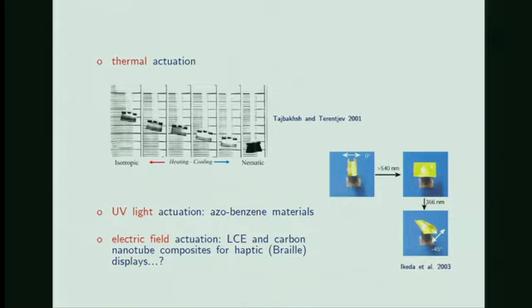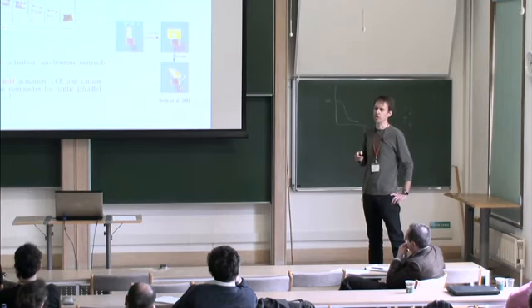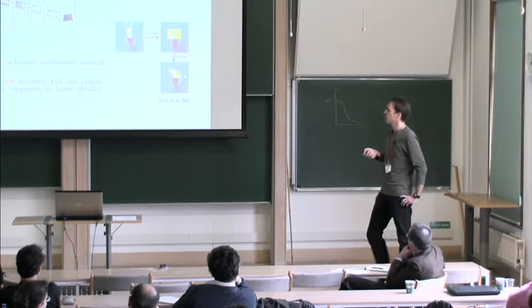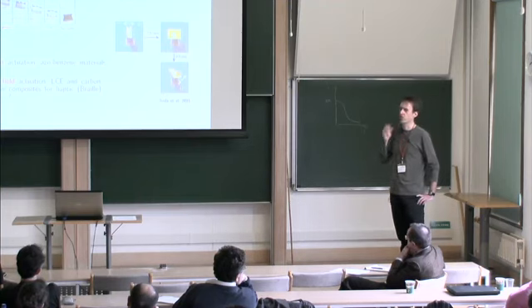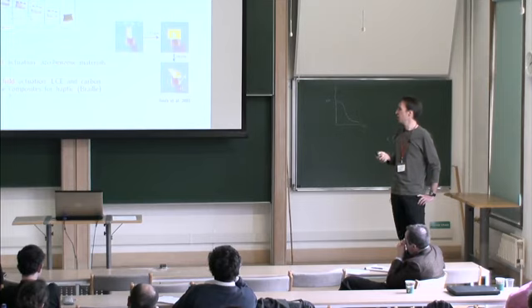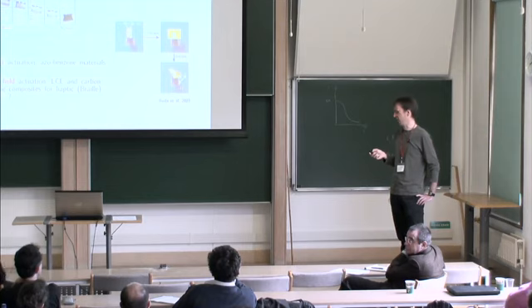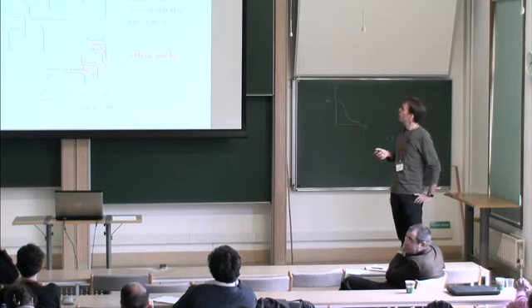Then UV light actuation. This can be done in so-called azobenzene materials, where double bonds between nitrogens can be found in different conformations, affecting orientational order. So you can switch between various orientations and affect the degree of order in your system, and this will again be reflected in macroscopic deformation. But what's particularly appealing is to try to actuate by switching an external electric field off and on, for example. It turns out that this is not so easy because enormously strong electric fields would be needed. But there have been proposals to introduce nanoparticles, carbon nanotubes for example, to enhance this effect.